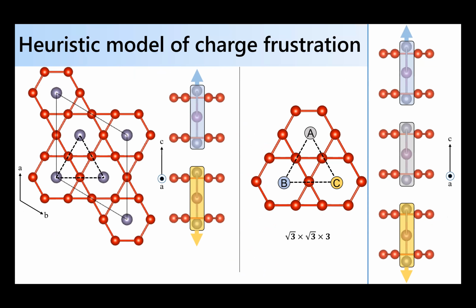But the lattice connecting the centers of the hexagons of a kagome network is a triangular lattice, right? And so that's a frustrated lattice, right? So if you just try and decorate it with one of these guys moving up, one of these guys moving down, then in principle, if you map this to some Ising degree of freedom within the chain, you'll have some residual entropy, and the lattice won't like that. But it can unlock an additional degree of freedom by just modulating further along the c-axis, where one of these trimers moves up, one moves down, and one doesn't move at all. Okay, so then you can decorate this as an ABC kind of three-state Potts type of model. And indeed, this is the experimentally realized ground state. Okay, so fine.